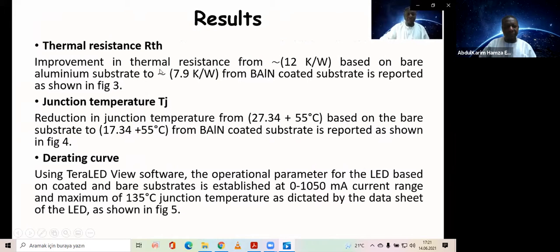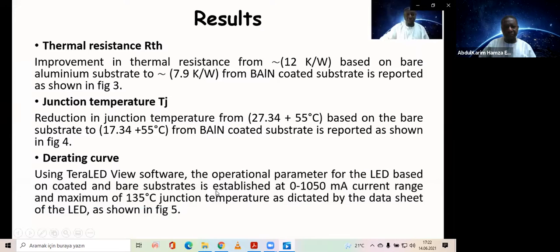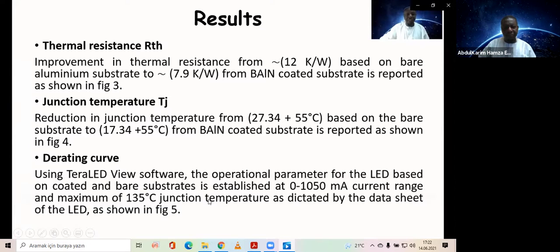Results: an improvement in thermal resistance from 12 degrees Kelvin per watt based on the bare substrate to 7.9 degrees Kelvin per watt based on the coated substrate is reported. A junction temperature reduction, from 27.34 based on the bare substrate to 17.34 based on the coated substrate, is also reported. And then using TeraLED View software, the operational parameter for the LED based on coated and bare substrate is established at a 0 to 1050 milliampere current range and a maximum temperature of 135 degrees C as dictated by the data sheet of the LED. The data sheet indicated that the junction temperature of the LED should not go beyond 135 degrees C.